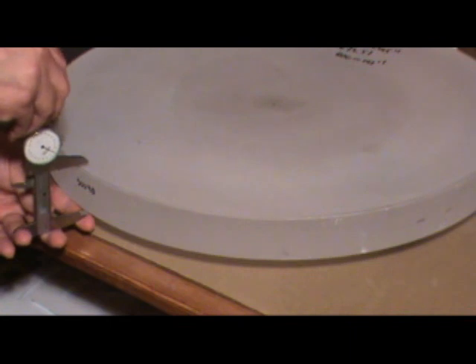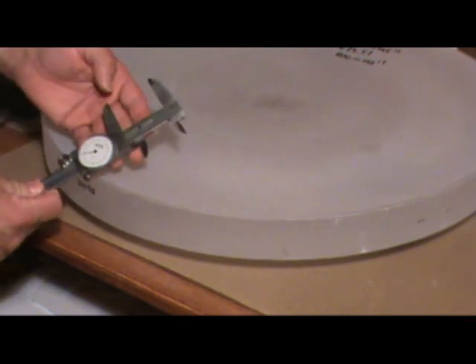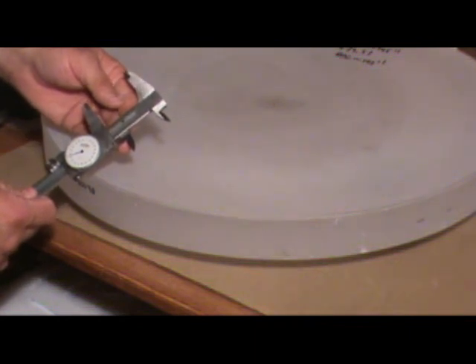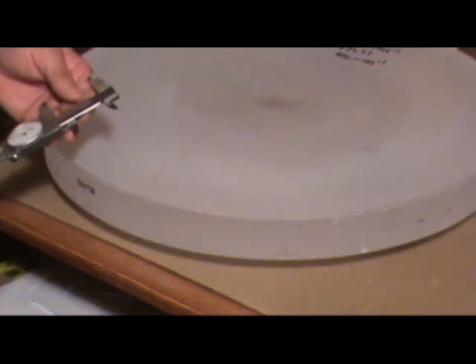Stretch it out a little bit. Put it on the edge of the mirror. And do the measurement on the dial, and this one is 1.745 inches, and that matches the 1.75 spec on the mirror, so thickness of this mirror is just fine.